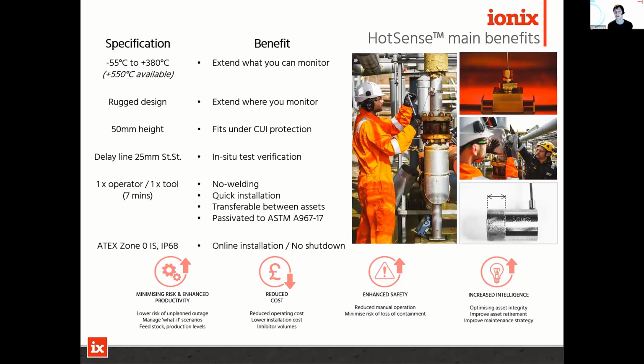The probe itself for the 380 probe has a 25 millimeter stainless steel delay line on the front. The delay line is there to allow you to take shallow measurements, but it also gives you, I suppose, a known reference reflector, and we can see that in some of the later slides, which is really important when you've got installed sensors, because you need to be able to potentially validate the measurements remotely. You can't take the probe off and put it on a test block and see what's happening when your measurements change.